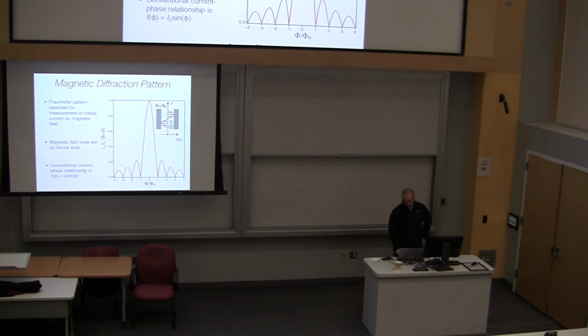But to shed a little more light on this, we also made junctions from tin telluride nanowires. These are the ones from Judy's group, grown at Yale. So you remember, we're now going to look at the magnetic diffraction pattern, which should have this Fraunhofer-like shape. There's a maximum at B equals 0, and there's lobes. Now, there are many ways to distort this by, say, having the supercurrent be stronger in one region than another, which can modify this pattern. And we can simulate this for all sorts of things that can go on in the junction. But one thing that is constant is that there's always a maximum in this critical current at B equals 0.